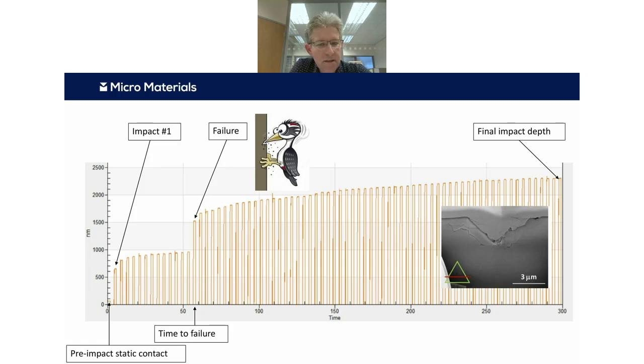So here's just a typical example of the sort of data that you might get off one of these repetitive tests at the same position. So this is actually taken from one of the tests with the cube corner indenter on the alumina sample that I showed the high strain rate from a couple of slides back. And here we can see we've got penetration depth into the material on the y-axis and time on the x-axis. And it's one impact every 4 seconds in this particular test. So we can see we have this very small depth right at the beginning of the test due to the static contact.